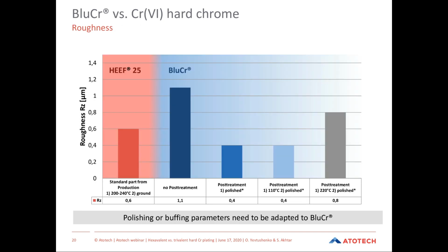Okay, very important also to compare the roughness. Roughness needs to be okay at the end. And as you can see, the parts deposited from blue chromium, just as plated without any treatment, have a bit higher Rz value. This depends, of course, on the substrate: what is the quality, what is the roughness of the substrate? But also due to a bit different growth mechanisms of layers from blue chromium, a bit higher roughness can be expected as plated. However, what is important to see here is that if applying post-treatment like post-grinding or post-polishing, it is possible to achieve even better results than for parts deposited from HEEF 25.